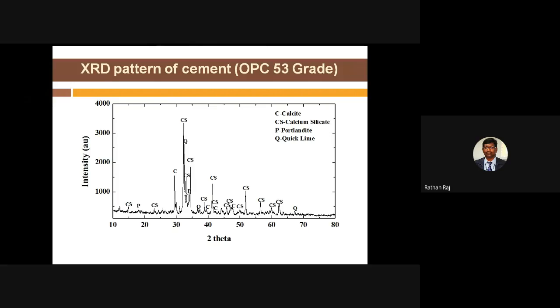So this is the XRD pattern of the cement, which will identify the peaks and the low curves. Each point will be identified. C is a calcite element. Wherever you see the C, it is all calcite element, and CS is calcium silicate. P is Portlandite, and Q is quicklime. Quicklime is nothing but calcium oxide. Calcium oxide is the calcium content. Now the CS content is the calcium silicate content.